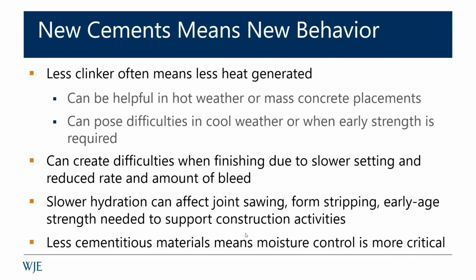It can create difficulties when finishing. We have slower setting. We generally have less bleed water. It can fool people. They can get on too early. They can trap bleed water. We see this problem emerging a lot on hard troweled surfaces where the crews that have developed this incredible empirical knowledge over decades are all of a sudden befuddled when they think the surface is ready to be finished and they get on it and all of a sudden they trap bleed water and we get delamination issues. So we've been sorting through that. Slower hydration can also affect when you can saw joints, when you can strip forms, when you can get on it, when you can drill dowel bars, tie bars, all of these things that have to be considered.